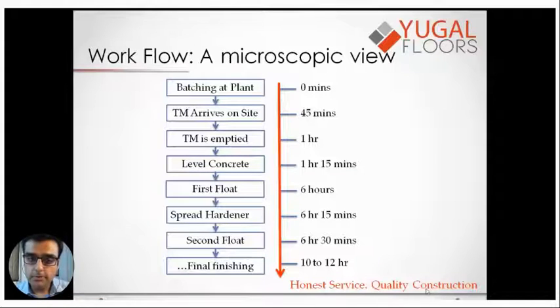And now I will talk about my process, how I work as a flooring contractor. So at time T0, you batch at the plant. It takes about 45 minutes for the truck to arrive on site. You take another 15 minutes to empty the truck. You take a further 15 minutes to level the concrete. So since the time the concrete was batched and you leveled it using a laser screed, it took you about 1 hour and 15 minutes. Then there is a gap of about 5 hours where the concrete just sits there, and slowly it is hardening, it is setting to be able to come to a position where we can actually walk on it and finish it. So we do our first float at about 6 hours.